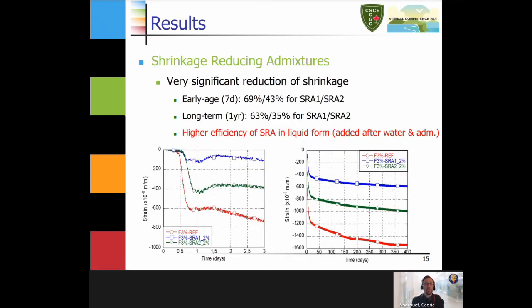Finally, when we use shrinkage reducing admixtures, remember SRA1 is supplied in liquid form, so it's added after water and admixtures in the mix. SRA2 is supplied in a solid form, so it's added with all the dry materials before water and admixtures in the mix. And we see that SRA1 in the liquid form is much more efficient in reducing shrinkage than SRA2. It leads to a reduction of almost 70% at 7 days for SRA1. So really much more efficient than the SRA supplied in the solid form.